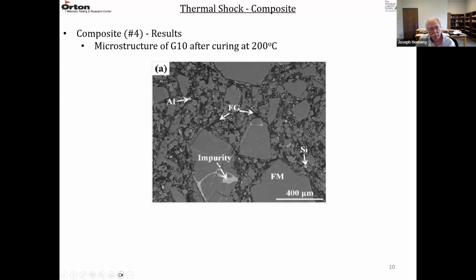You can see on this coarse grain and this one, you can see the white areas. That's an impurity, usually a calcium silicate. And that etch really shows up where the grain boundaries are. So this portion was probably a single crystal, and these were also single crystals, but these are crushed aggregates. So fused MgO, some impurities. The black regions are the flake graphite. And then there's a small spot here. That's an aluminum metallic particle. And then the other small spot here is a silicon metallic particle.